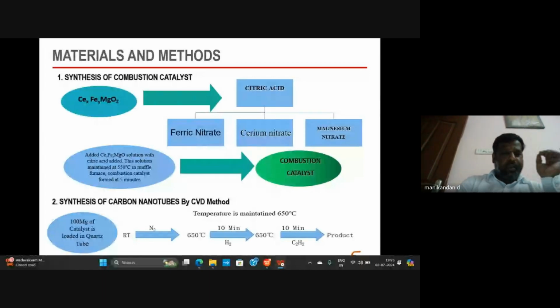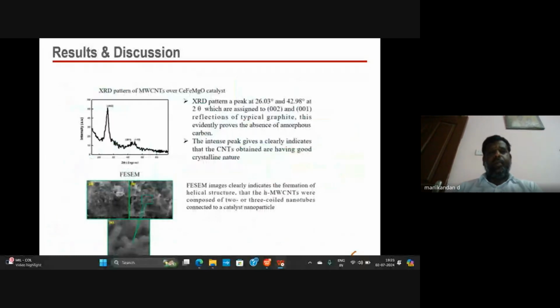These are the materials and methods. First step, synthesis of the combustion catalyst. CeFeMgO is set. One molar solutions of ferric nitrate, cerium nitrate, magnesium nitrate, and citric acid were added. The solution was added and maintained at 550 degrees Celsius in a muffle furnace. The combustion catalyst formed in 5 minutes. This is the combustion catalyst I prepared. And step 2, synthesis of carbon nanotubes using the CVD